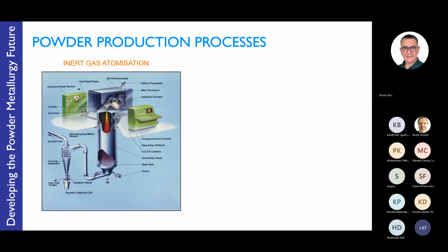The raw materials are typically alloyed in a coreless induction furnace. This is often prepared in a melting enclosure of inert gas in many cases. So that often provides a partial pressure to protect the molten material from oxidation, for instance, and reduce the levels of slag generation and oxides. Often using nitrogen gas, which is, of course, the lower cost gas compared to argon atomization, but both are typically available on these types of facilities.